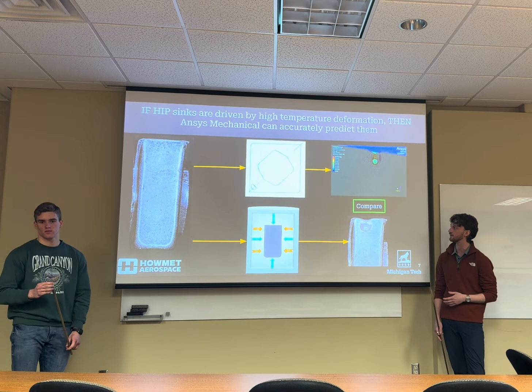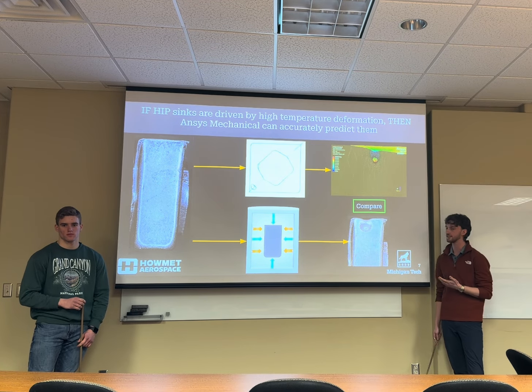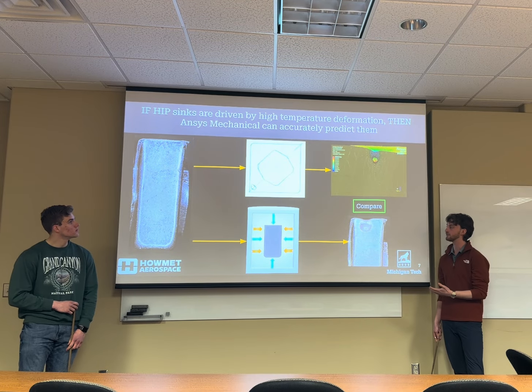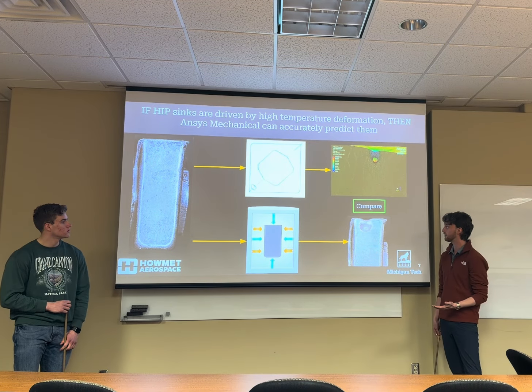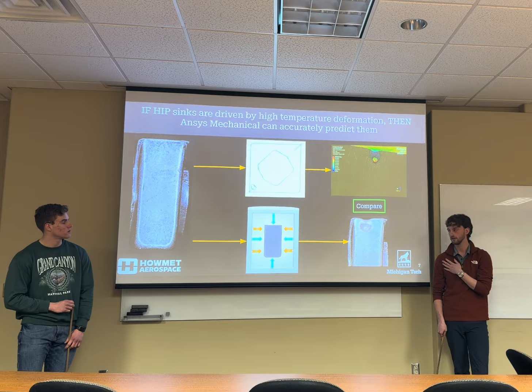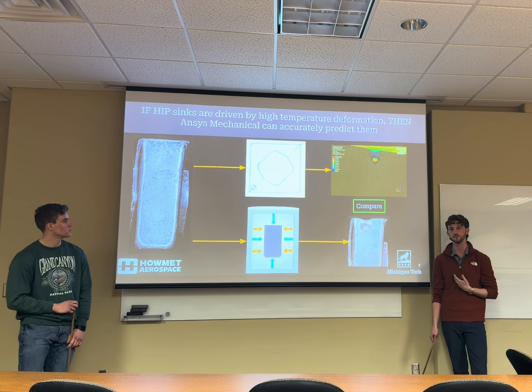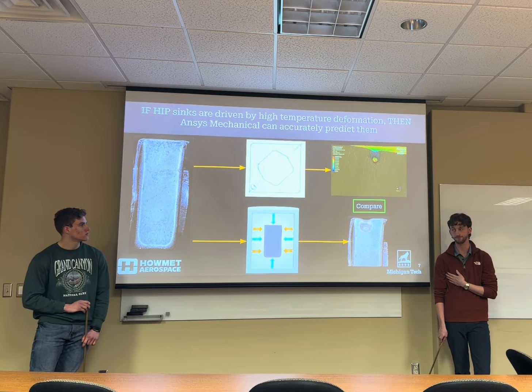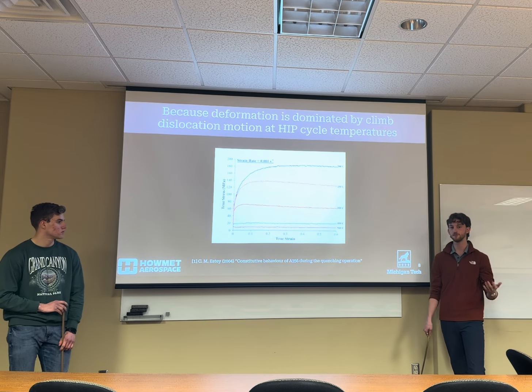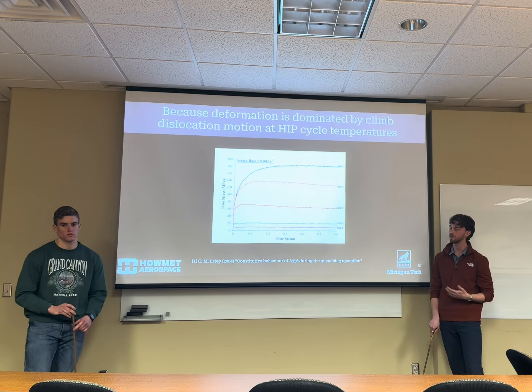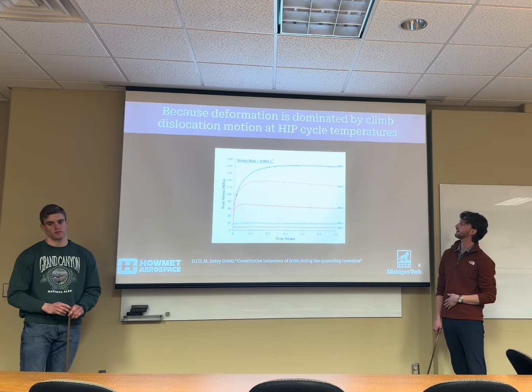Now, if hip sinks are driven by high temperature deformation, then a finite element analysis software like ANSYS Mechanical can accurately predict them. And the whole goal here is to produce a casting here on campus, send it to Howmet for CT, where we can get a CAD model, which we can then put into our software to model a hip sink. And then we also do the process here on campus to get a physical casting for comparison. Now, this is because at these temperatures, deformation is driven by climb dislocation motion.